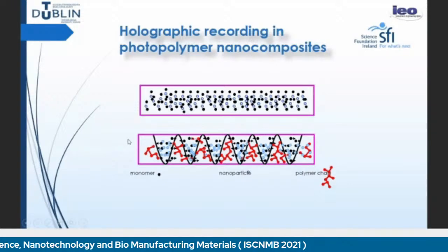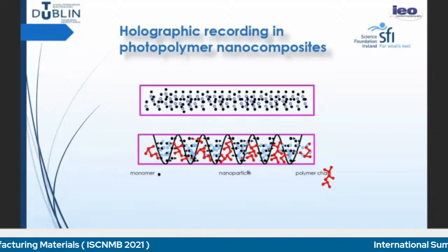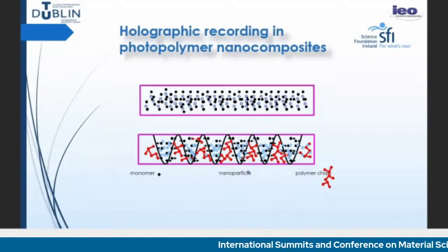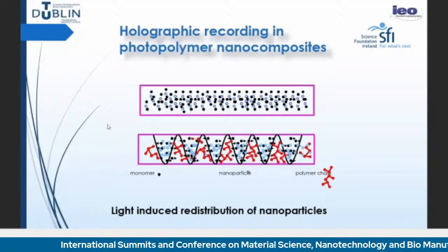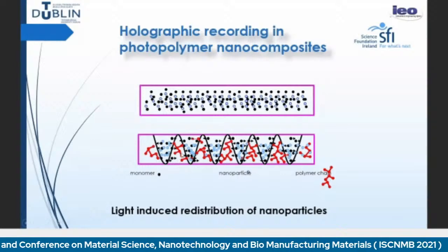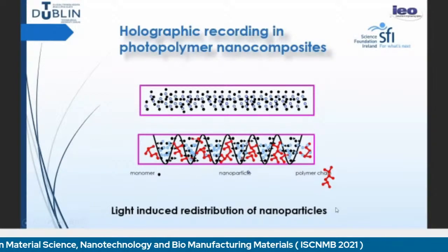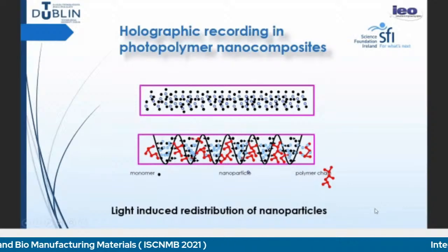But other groups have investigated this, and where the nanoparticles end up very much depends on the balance between the diffusion and the rate of polymerization of the material. So in some systems, if the polymerization is very fast, they may be trapped in the bright fringes. But the important thing is that they are redistributed.